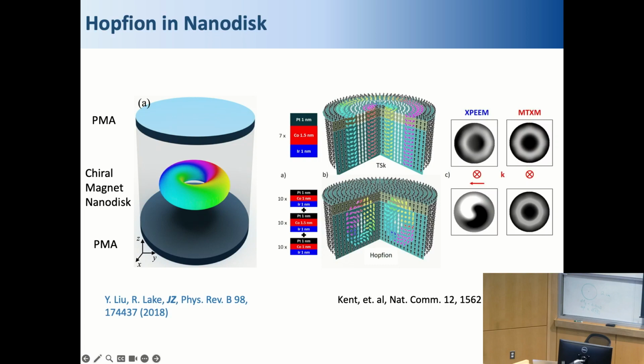You can already consider that a single crystal, right? Because you have a superlattice. That's not a single crystal, but it's just one combined hopfion. Yeah. So we're going to put lots of those together to make a hopfion lattice. So I'm leaning towards the idea that maybe we should look into a frustrated magnet with DM interactions, with some non-centrosymmetric frustrated magnets, because this hopfion breaks inversion symmetry. So we need some elements to break that symmetry.